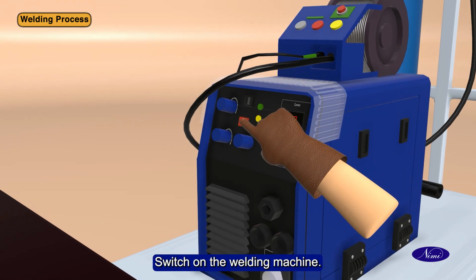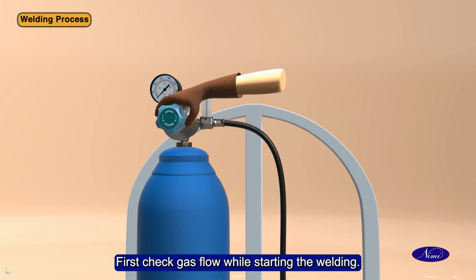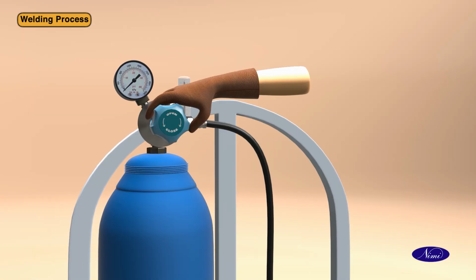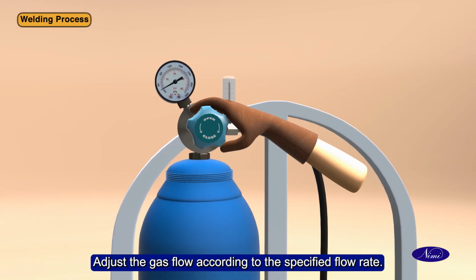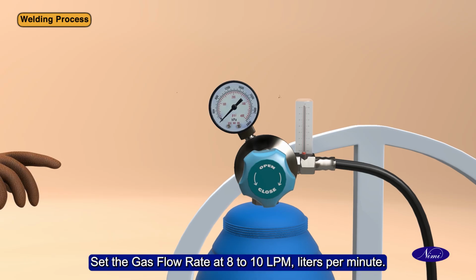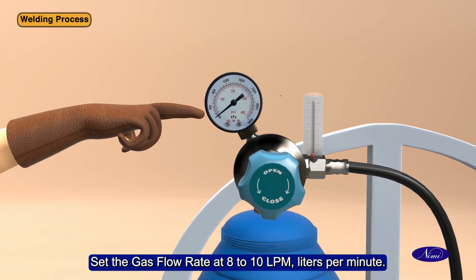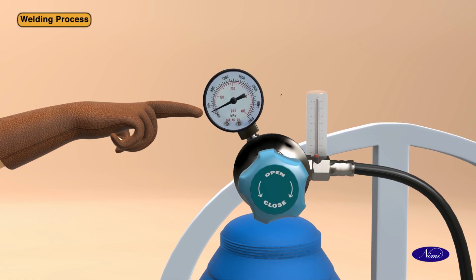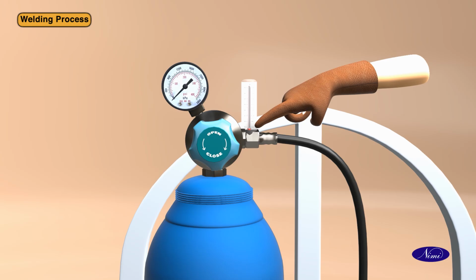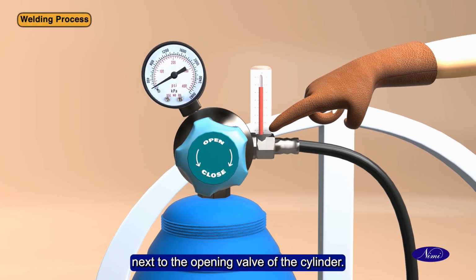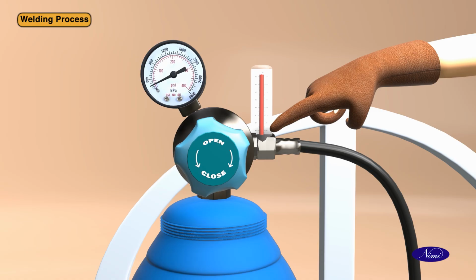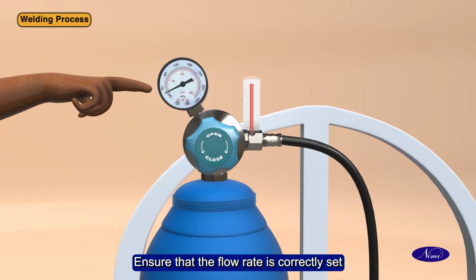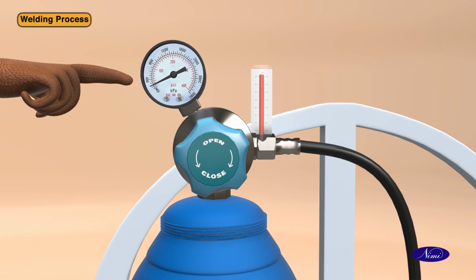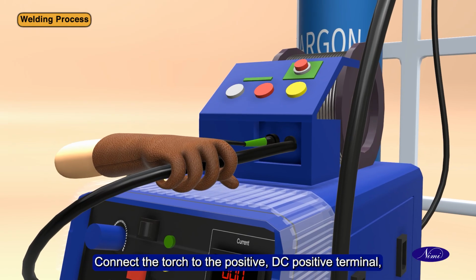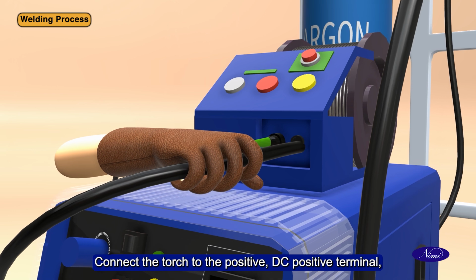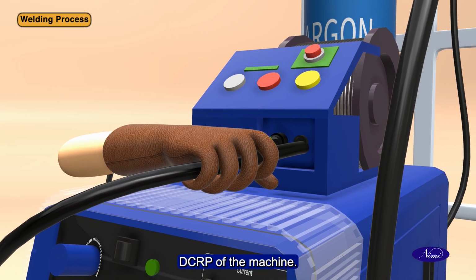Switch on the welding machine. First, check gas flow while starting the welding. Adjust the gas flow according to the specified flow rate. Set the gas flow rate at 8 to 10 lpm, liters per minute. See the flow rate in the flow rate tube next to the opening valve of the cylinder. Ensure that the flow rate is correctly set for the welding process. Connect the torch to the DC positive terminal, DCRP, of the machine.